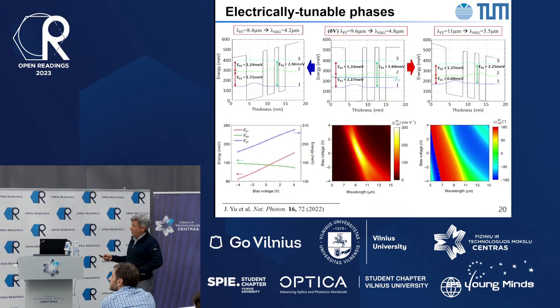After all, you apply bias to your quantum wells and energy levels shift. Energy levels shift, your quantum mechanical expression for the nonlinearity starts changing, and as you change the resonant denominators, the phase of the complex nonlinear response changes, and that corresponds to the change in the phase of the response of the antennas. So again, this is an implementation where these quantum wells can now be biased, and when you apply certain bias voltage, they shift in a certain way, and you can predict how the value of the optical nonlinearity changes. Well, the amplitude will change as well because you're moving in and out of resonance, but also the phase will change.